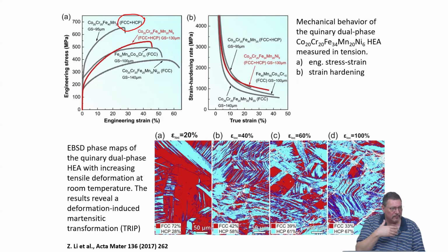And it's basically, when we think of how twins originate, this is coming from the stacking fault, right? So you create the first stacking fault, and then when the second stacking fault goes along the same plane direction, but a parallel plane, then you basically have a twin, a mechanical twin. And this is how twinning-induced plasticity works. And when you see this curve here, so let's say this one here,